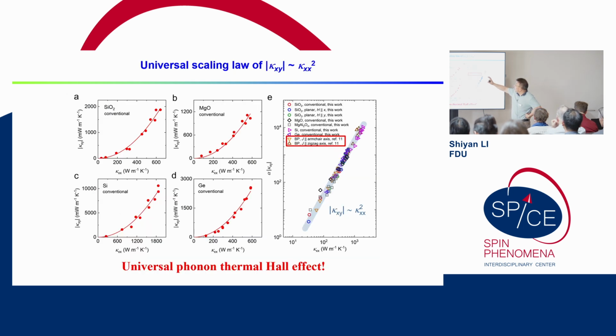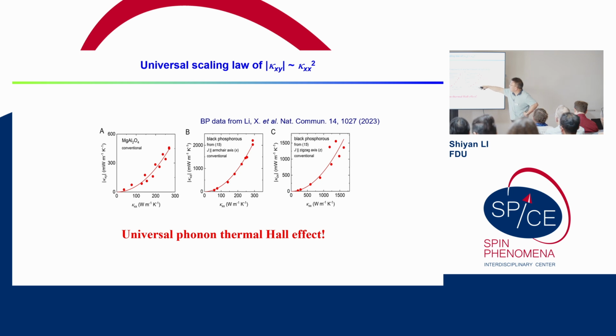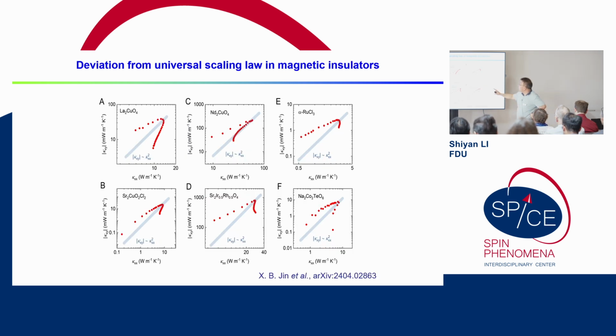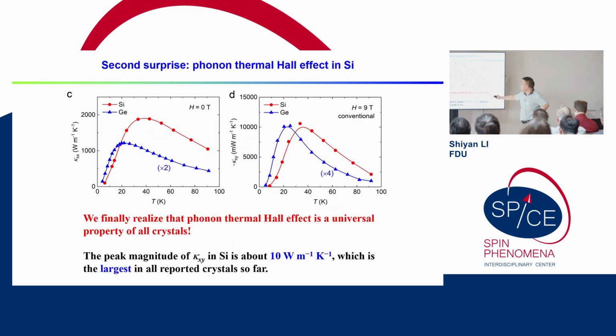And also, we find this universal scaling law. So if we plot this kappa xy versus kappa xx and fit it, it seems to follow this scaling law. Not only for our crystals, and also for this black phosphorus measured by Professor Behnia's group. But for other compounds, there's magnetic stuff and a lot of impurity, there's some deviation from this universal scaling law.